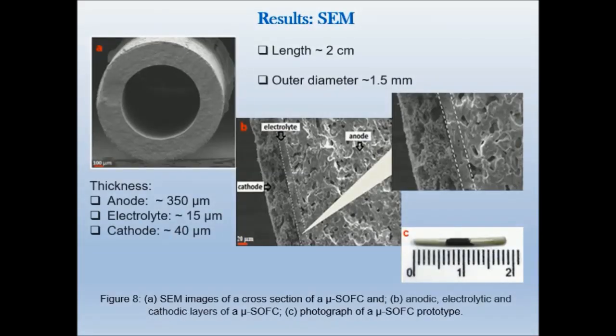Now I will present some of the results of a microtubular solid oxide fuel cell prototype we have fabricated. Such a device had a length of 2 centimeters and an outer diameter of 1.5 millimeters. In this slide, some SEM images are shown from which the anode, electrolyte, and cathode thicknesses were estimated. Based on the SEM images, it is clear that the anode and cathode are porous. Porosity estimated from SEM images is in the 30 to 40% range, which is adequate for operation. And the electrolyte layer has no open porosity, needed to prevent gas mixing.